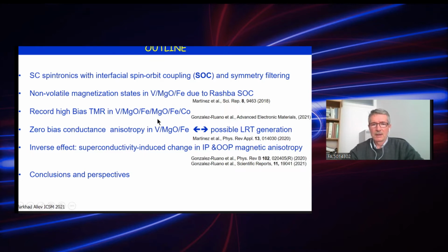Very recently, published just a couple of days ago in Advanced Electronic Materials, we also showed that the normal state properties of the system exhibit amazingly high magnetic tunneling magnetoresistance at very high electric fields. So, due to our spin-orbit coupling, we are able to create high-bias, very sensitive magnetic field sensors, for example.